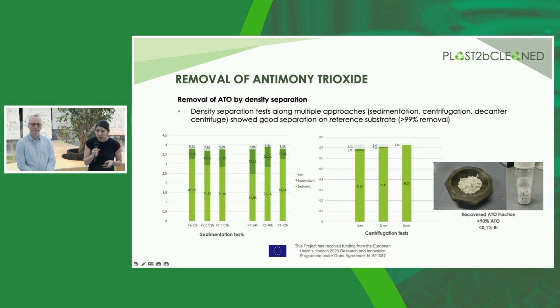You can see on the left-hand side picture that sedimentation tests were performed as well as centrifugation tests on the right-hand side, whereas the centrifugation test led to better results. The drawback of the sedimentation test is the long time needed to achieve significant separation of antimony trioxide from the polymer solution. And on the pictures completely on the right-hand side, you can see the recovered ATO fraction of high purity and a low bromide content.